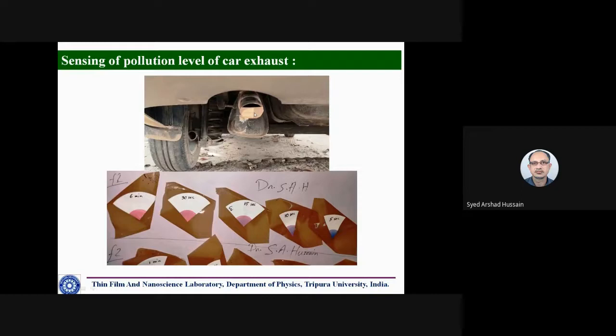Initially we prepared the film using suitable organic material and clay. Then we exposed it under UV, and it converted into blue. Then this blue film we put it here. You see, with time, it started responding in 5 seconds. Then in 10 seconds, 15 seconds, 30 seconds, it totally converted to red.